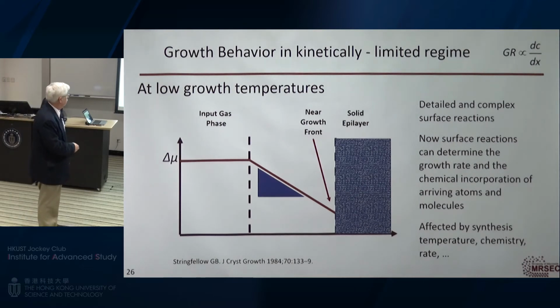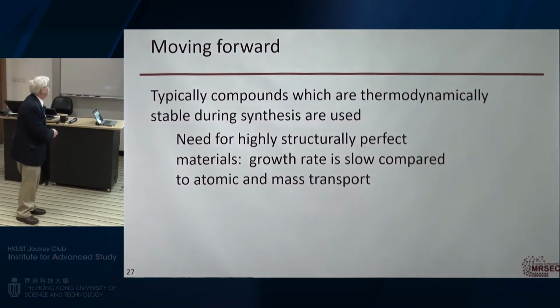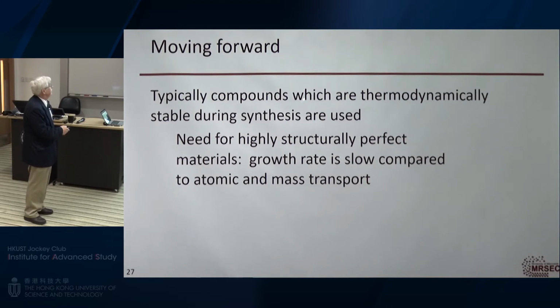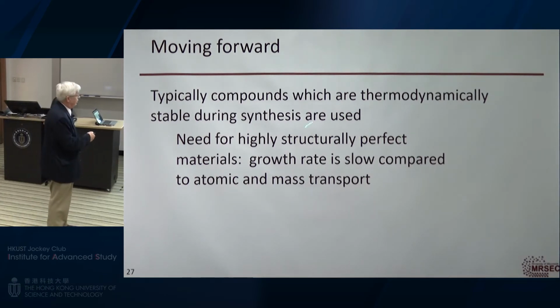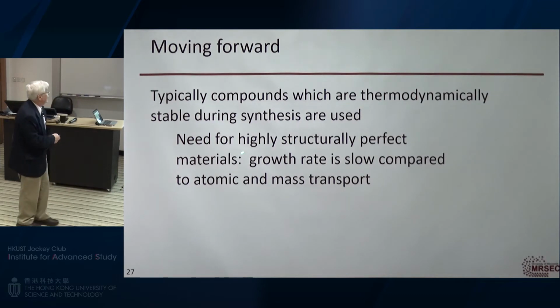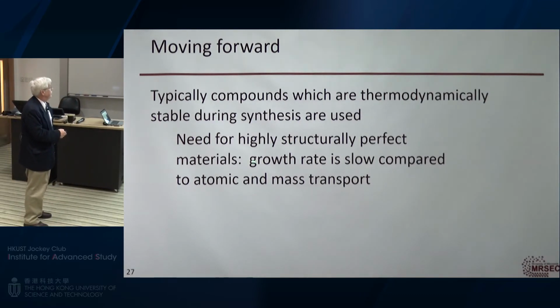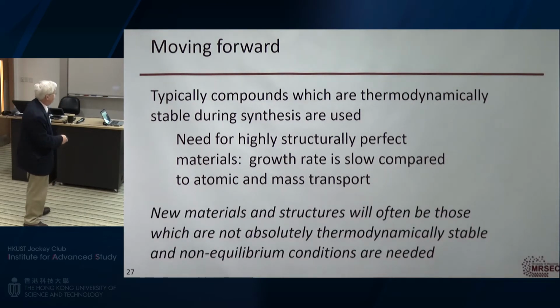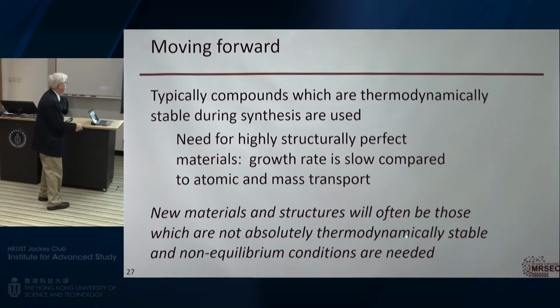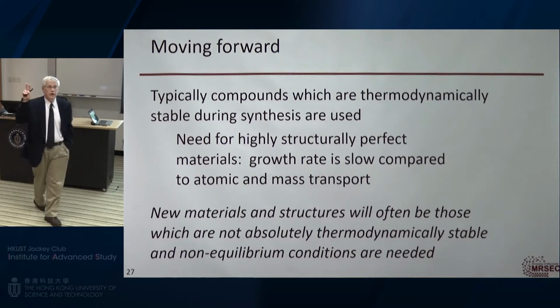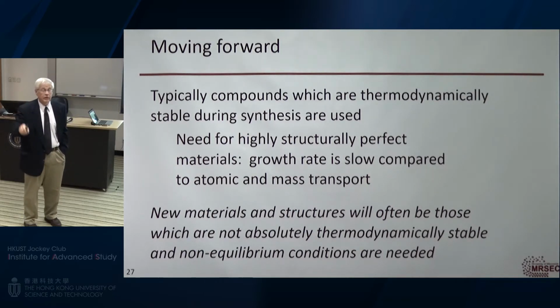And we're going to show you two ways we can do that to create materials that aren't at equilibrium. So moving forward, typically compounds that are thermodynamically stable during synthesis are used. Silicon, gallium arsenide, are these nonlinear optic materials that are in this. We need highly structurally perfect materials so the growth rate is slow compared to transport. New materials and structures will often be those that are not absolutely thermodynamically stable, and non-equilibrium conditions are needed to make them. So we're going to show you two non-equilibrium ways we can make these materials.